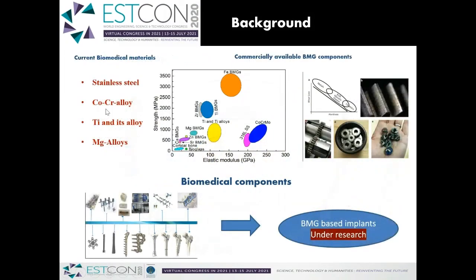The material which we adopted, which is called a bulk metallic glass, is an amorphous material, or we can say non-crystalline material, which has some unique properties when compared with currently used biomaterials like stainless steel, cobalt, chromium, titanium and its alloys, and magnesium alloys. This figure demonstrates the relationship between the strength and the elastic modulus. As you can see here, this is the cortical bone. Most of the BMGs are much closer to cortical bone in terms of elastic modulus. This will help in the stress distribution and prevent the effect of stress shielding due to much difference in the elastic modulus when conventional biomaterials are used.